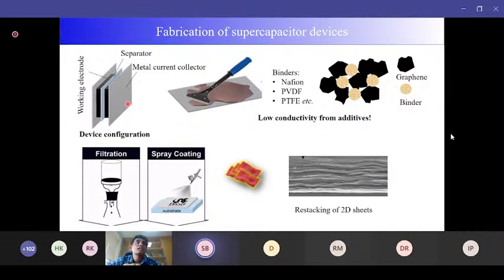Now the question is how to construct one electrode, how to put your material on this metal collector. Industrially, the most common method of putting the material over this current collector is printing. In this printing, the material, suppose graphene or MXene or polyaniline, is first mixed with some binder. Binders are like a glue. Nafion, PVDF, PTFE, these are the glues. They just mix it so that you have some mold kind of thing. This mold you cast over this metal plate, and then you construct this device.